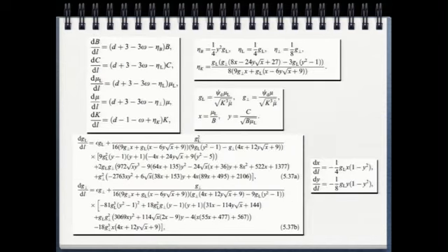They are those we discussed earlier: the bulk modulus, longitudinal shear, transverse shear, Frank constant, and this cross coupling. So these parameters transform multiplicatively, and we work out all these flow equations for these parameters. G_L and G_perp, again, are dimensionless ratios. The flow equations for G_L and G_perp are really horrendous. And you have another two dimensionless parameters, x and y, which are somewhat simpler.